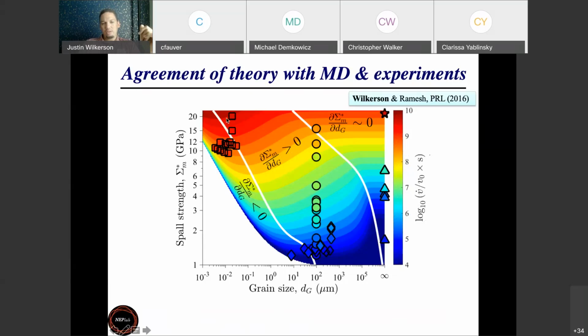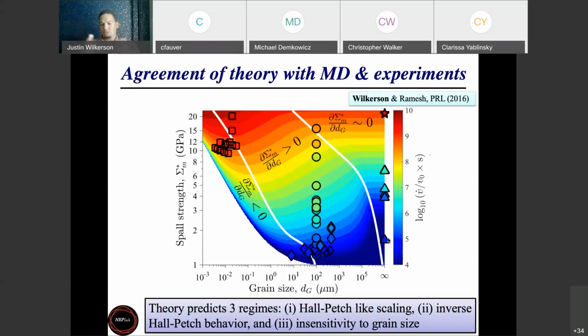These square data points over here are from molecular dynamics calculations, and these are single crystal spall experiments on the right. And what this is showing is how spall strength depends on grain size in this really strange, anomalous way. It's very non-monotonic, as you can see here. So if you follow one color, that's a single strain rate. So let's just follow this cyan color here.